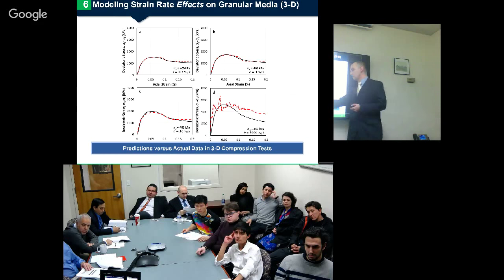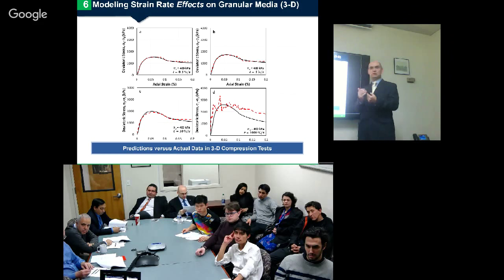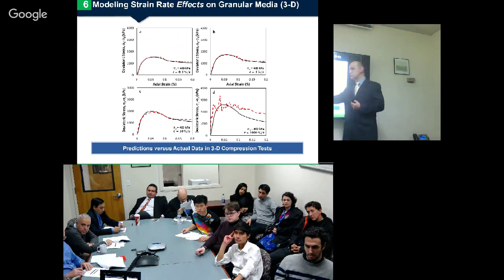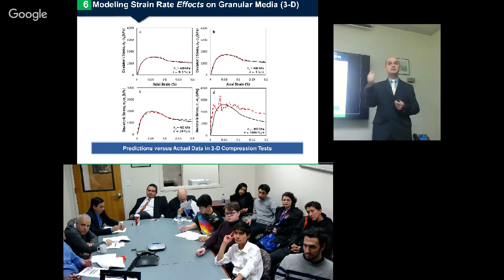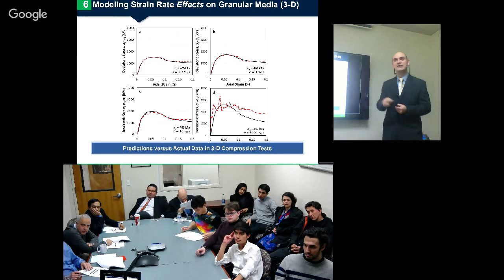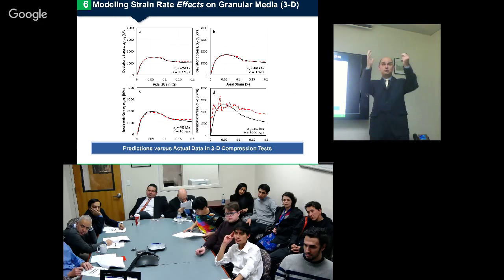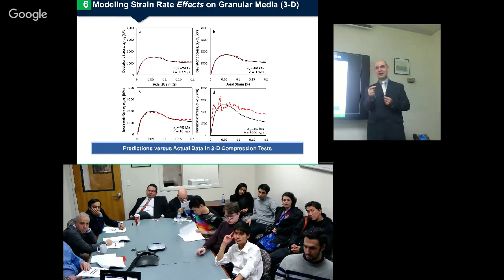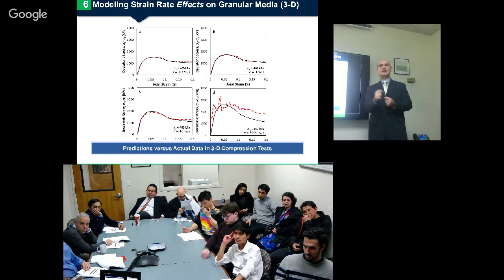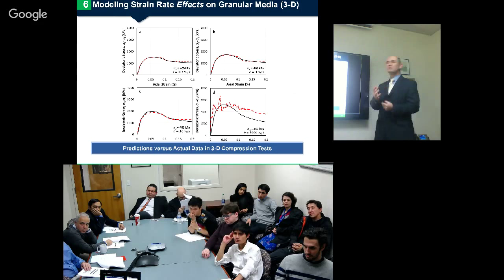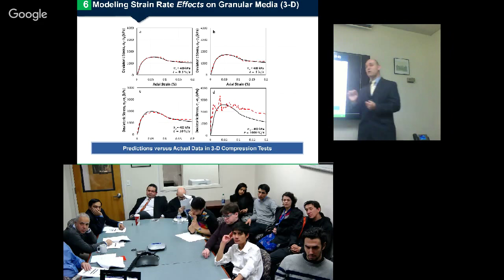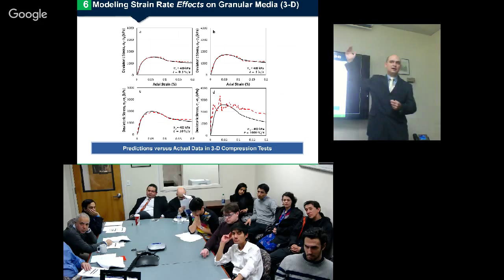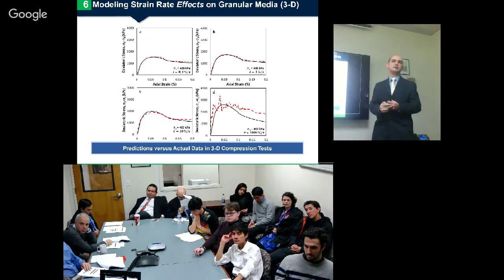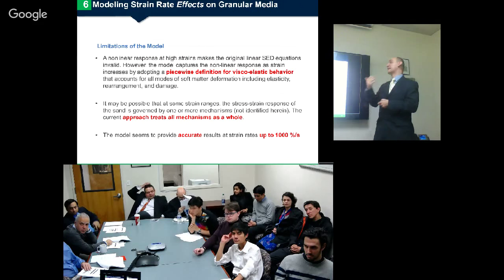And again, I had to take data that were not supposed to be part of this test, because it might be the sensors of the velocity that started early. When you drop the weight, you have to set a flag or a sensor that starts taking the impact velocity. And sometimes these curves before the starting point will give you weird results that I didn't include.